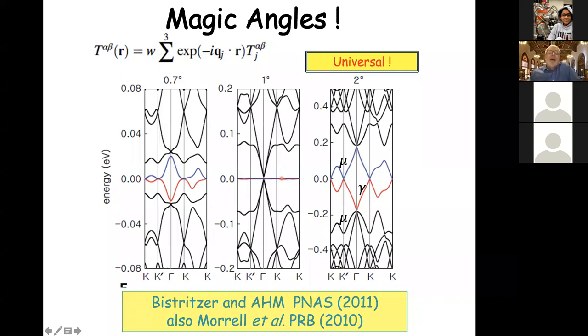something magic happens, something that was discovered numerically from this model. At this twist angle, the energy of the lowest energy graphene states, and as I'll emphasize later there are actually 8 states here, depends on momentum. And you can see that the dependence of energy on momentum practically disappears at these magic twist angles. What that means, of course, is that the electron velocity has dropped essentially to 0. If you include details, you'll find that it's dropped by maybe a factor of 1,000 or 10,000 relative to the large velocity of the isolated graphene sheets, which give these strongly dispersive bands at other twist angles, particularly at larger twist angles. And only at discrete twist angles does the velocity drop to very small amounts.